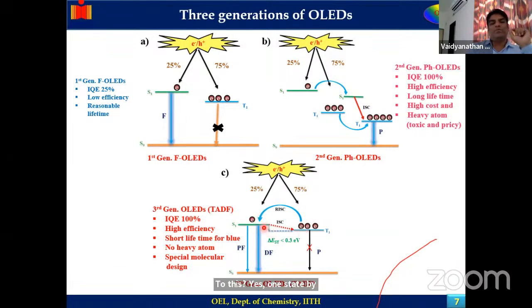When you go from S1 to T1, it's called inter-system crossing. When you go from T1 to S1, it's called reverse inter-system crossing. So basically, one can get an internal quantum efficiency of 100%. The efficiency can be high enough, with short lifetime for blue, no heavy metal ion involved, and special molecular design is required to get a desired property.